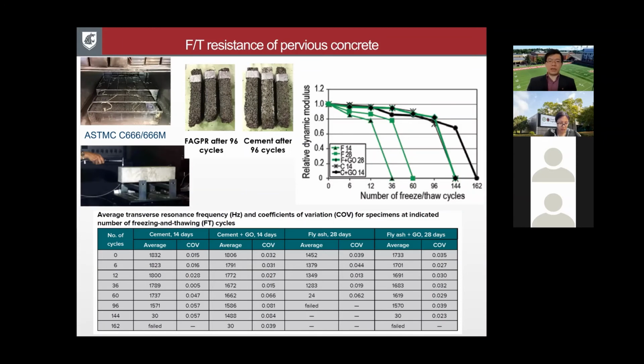So, salt scaling is a very complex exposure. You involve both the chemical attack and the physical attack. So we try to separate the two. So we try to do the freeze-thaw without any de-icer and see what's going on. And again, the similar story is that the geopolymer pervious concrete behaved as good as the cement-based pervious concrete, but still not as good as the geo-modified cement pervious concrete. Because if you look at failure, the first 2 groups I mentioned failed at 144 cycles of freeze-thaw, and the other one, the best one, the geo-modified cement pervious concrete, failed at 162 cycles.